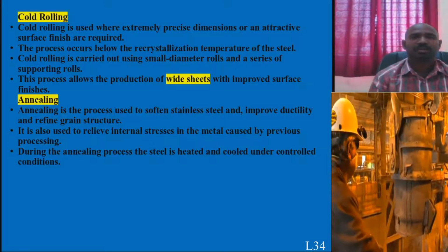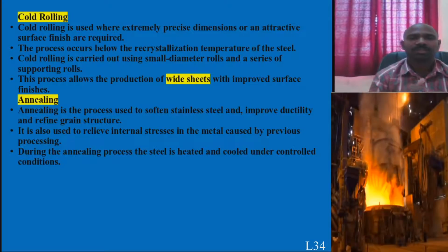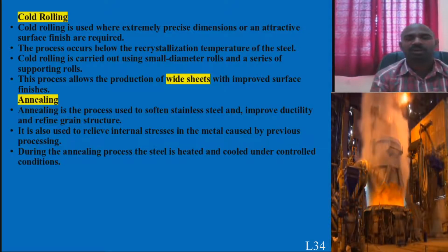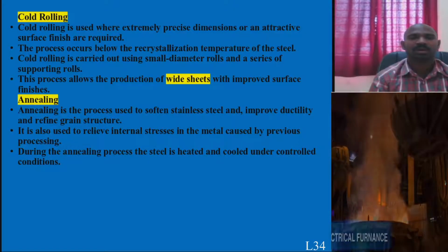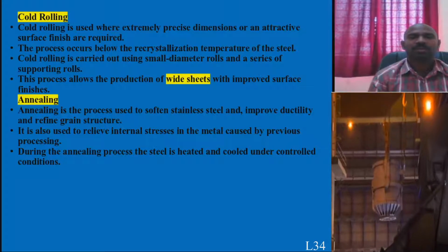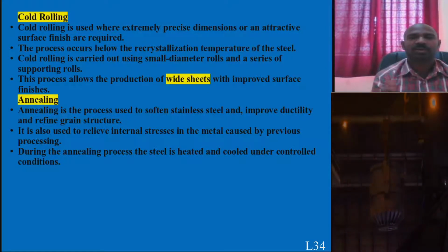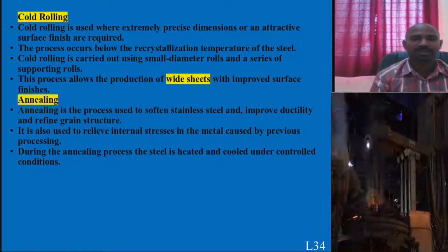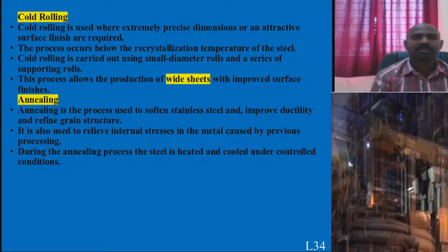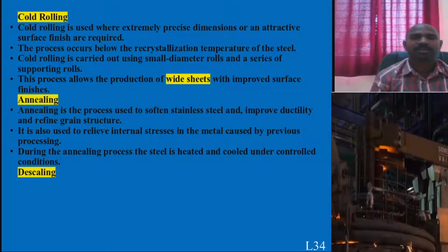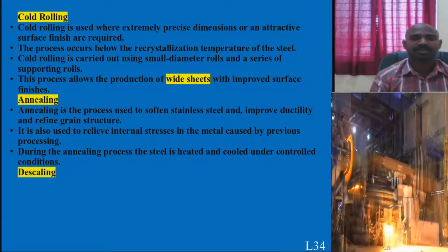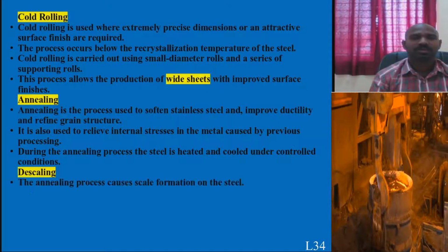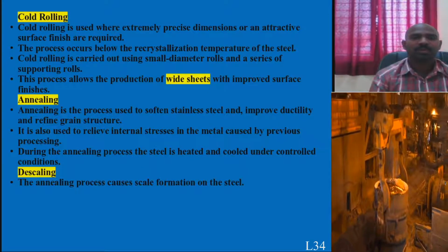And this annealing process is done in controlled cooling conditions, which is nothing but furnace cooling. There will be a box, large box type furnace, where the material is kept for 1 hour or 2 hours depending upon the application and grade of the steels and subjected to annealing process. One of the disadvantages of annealing process is it leaves scaling on the goods, on the products.